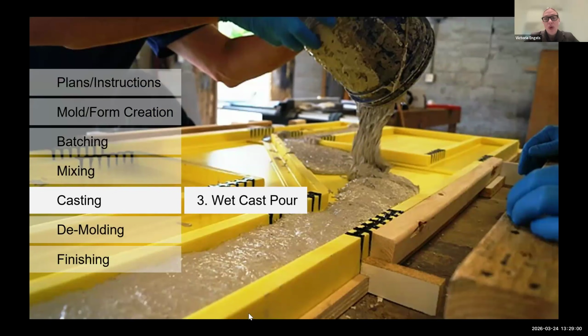And the final method is called wet cast pour, or SCC pour, SCC being an acronym for self-consolidating concrete. With this method, a low viscosity mix is poured directly into a form. This process typically requires some level of agitation to accelerate consolidation and remove air bubbles, as they're going to result in small holes on the surface of the concrete. This can be achieved using a vibrating table.